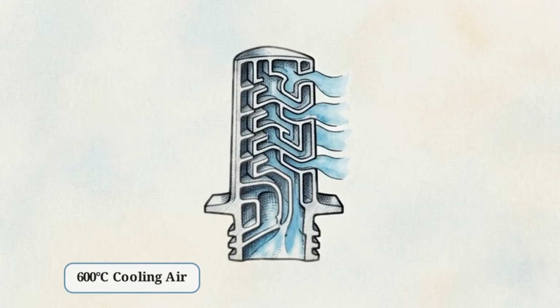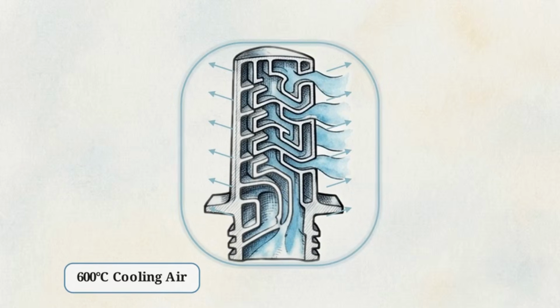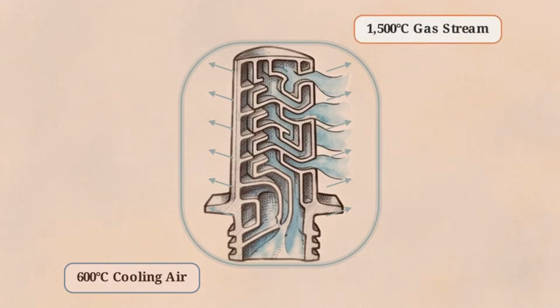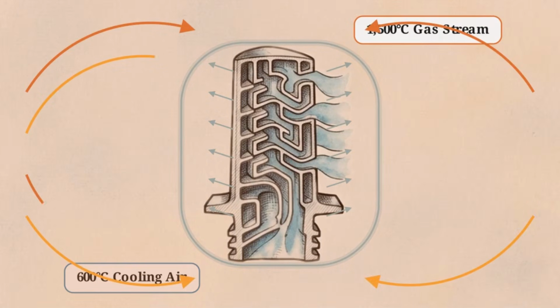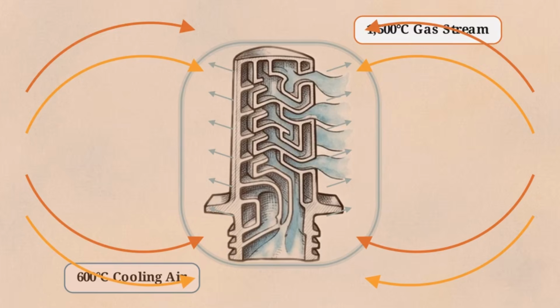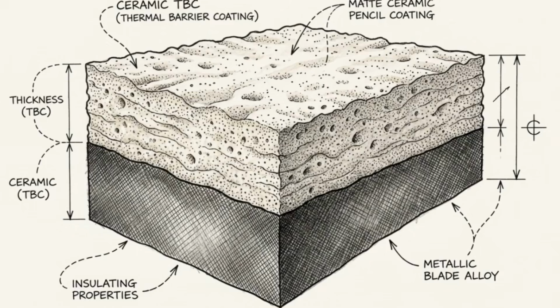Air from the compressor is pushed through this hollow core. It bleeds out of tiny microscopic holes on the surface in a process called film cooling, forming a continuous protective boundary layer over the metal. As a final layer of defense, the outside is sprayed with a 1/4 millimeter thick ceramic coating.